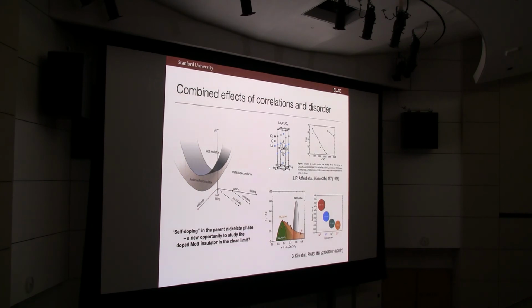And so this is both an old and new story. It was already long understood that this cation disorder and the size disorder was important. This is an early paper by J. P. Attfield. He took a 214 cuprate and mixed all sorts of different things such that the overall doping level was the same, but the variance in the A site cations was varying, and you could see that TC was linearly related, approximately, with this variance. And more than 20 years later, this still is bearing fruit.